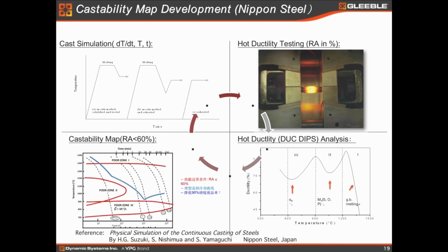Actually, at that time, 45% of the slab had to be flame treated to get rid of the surface defects. It's wasting the metal, the energy, and the time, and there is no way you can do continuous casting anymore because the temperature is going down, right? So they have to minimize the cracks. The way they did it is by doing 18 months of testing using this technology.